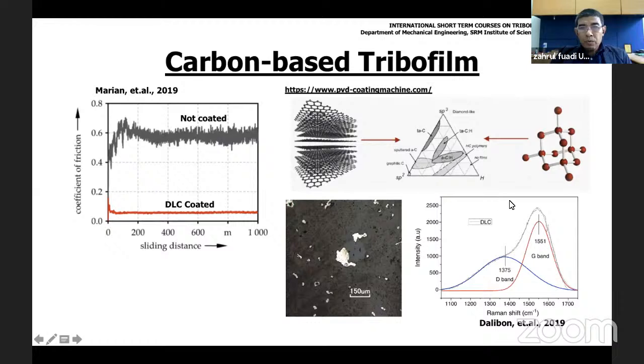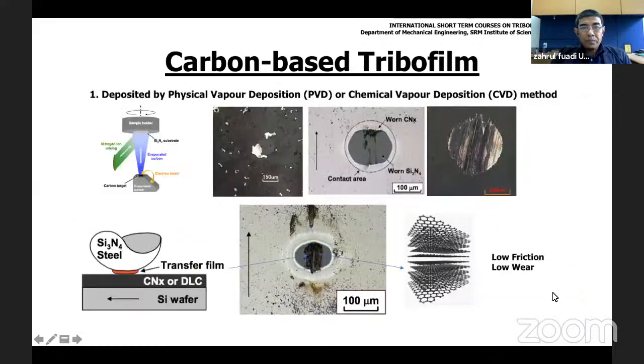In order to study the structure of the coating, we can use Raman spectroscopy. Such a coating is shown by two peaks here, the D band and the G band. So this kind of carbon-based tribofilm we can use to coat the surface to have low friction and wear. Then this carbon tribofilm can be produced on the contact interface by three methods.